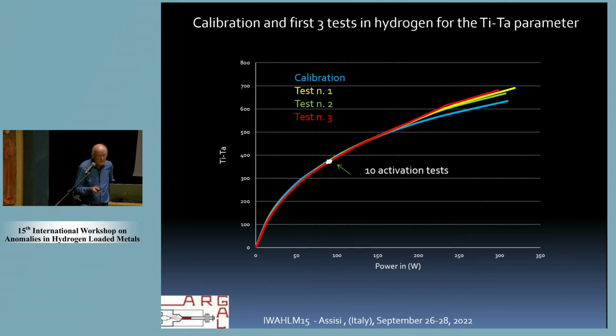Here in this slide we can see the comparison between calibration, the first test in yellow, the second test, and the third test. Consider that the third and second test have a common part from ambient temperature to 500 degrees. All these tests gave this inflection of the curves that are a signal of excess heat production.